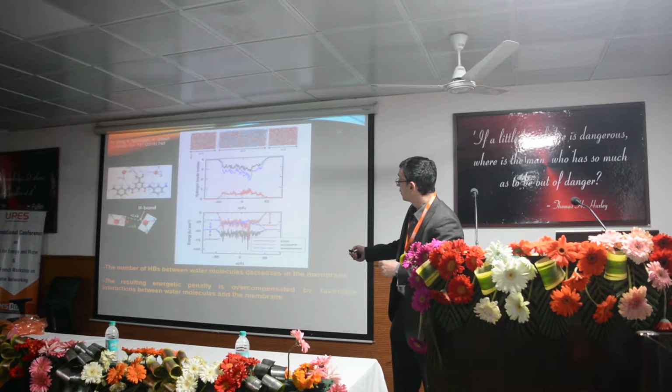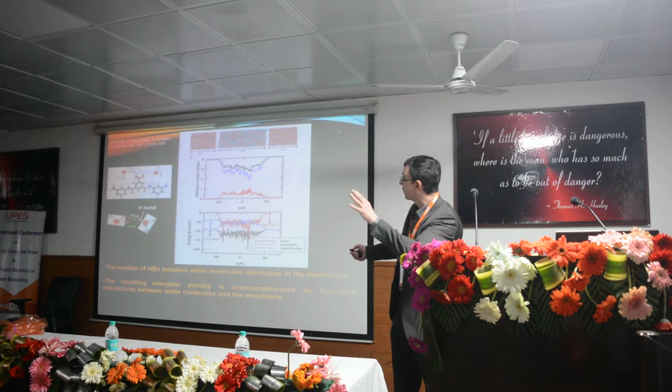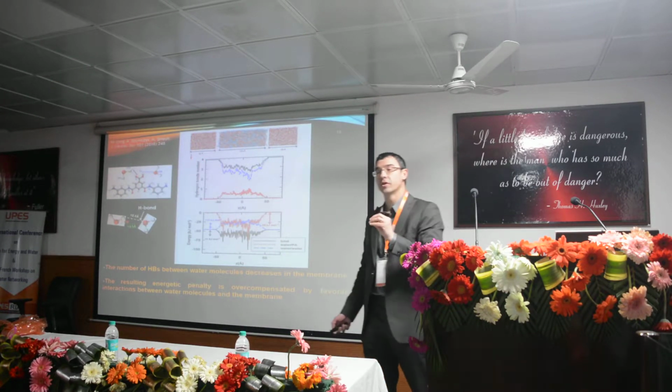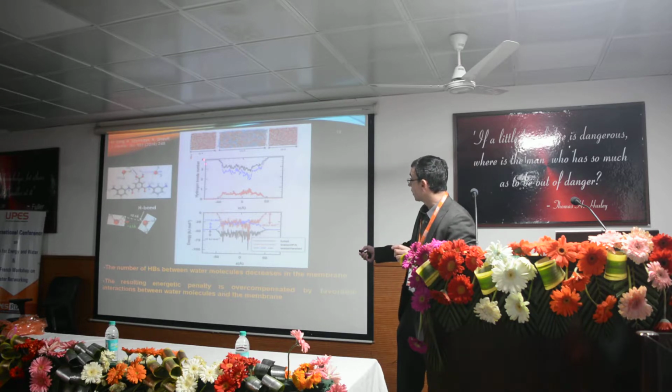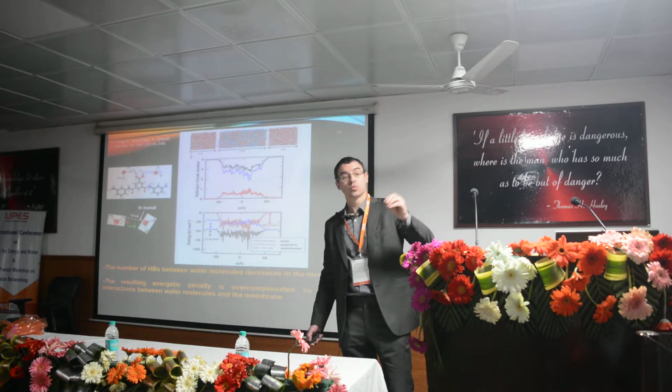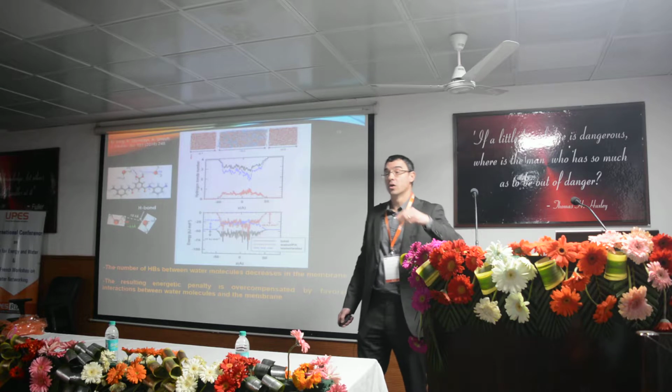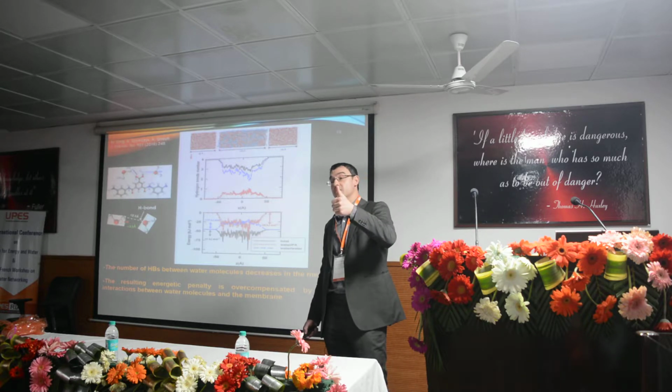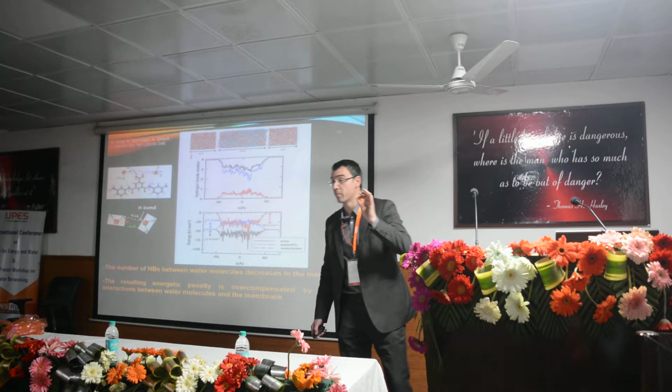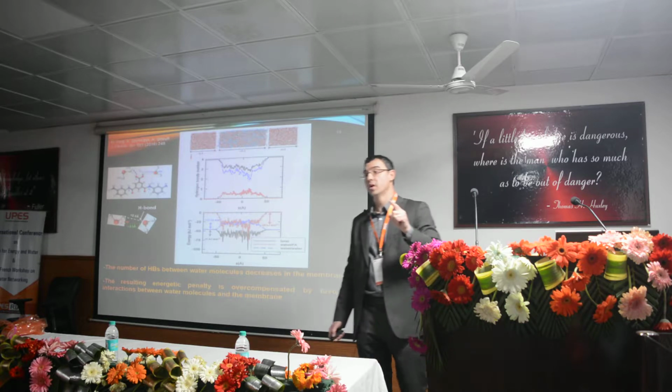Characteristics. So roughly 3.8, say roughly 4 H bonds per water molecule. But you can see a dramatic decrease of the number of H bonds when water molecules enter the membrane. Basically, the number drops down to approximately 3. So it means that each water molecule loses 1 H bond.